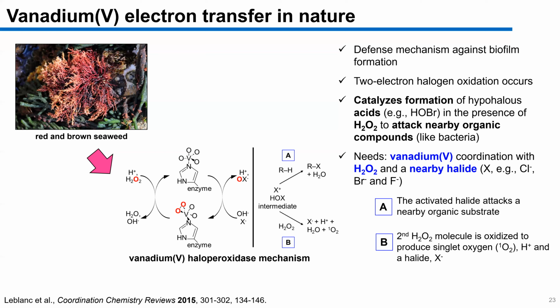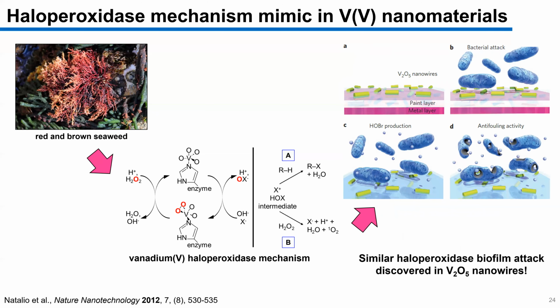So in our system, we were adding in hydrogen peroxide and we observed the formation of singlet oxygen. And for that halide that we need, if you recall, when you generate the V2C MXene material, we used hydrofluoric acid to etch away the aluminum layer. The literature surrounding MXene synthesis suggests that when you use hydrofluoric acid to etch away the aluminum layer, you get nanosheets that are terminated in fluoride compounds. We've done purification steps to make sure we don't have a lot of excess fluoride trapped within the different V2C layers, but there is some residual fluoride present. And this may be that nearby halide that's needed to complete a mimic of this vanadium haloperoxidase enzyme.